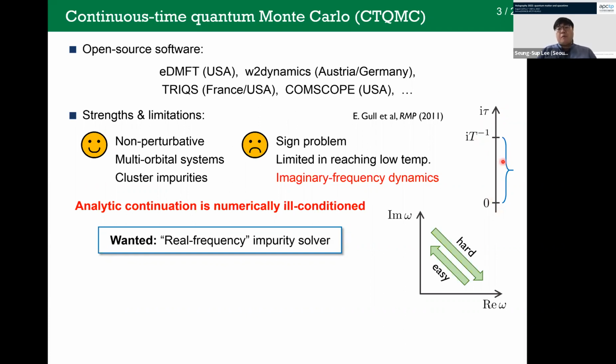So basically it provides the dynamical properties as a function of imaginary frequencies. But to compare with experiments, we should obtain the real frequency data, because in real experiments, one measures the data as a function of real frequencies. So one should perform the analytic continuation on this numerical data residing on the imaginary frequency axis. If it were an analytic calculation, then it would be simple, just a change of variable. However, for numerical data, it is very hard. Indeed, it is one of the famous inverse problems.